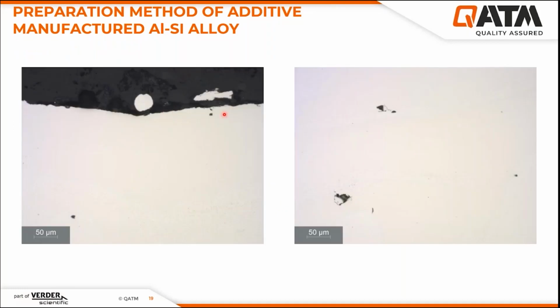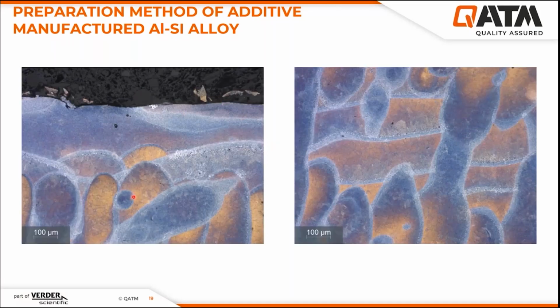Now you can see the edge without rounding in the non-etched position, and also on the right-hand side we can see the core area. After etching, we can see the outline and also the pattern and the spacing between the outline and pattern, and also the different laser layers under the optical microscope.